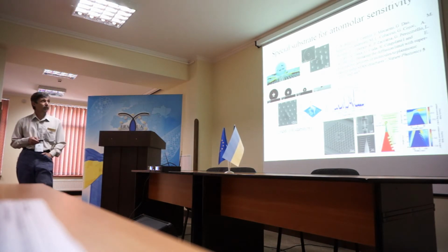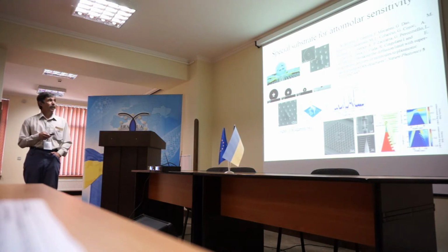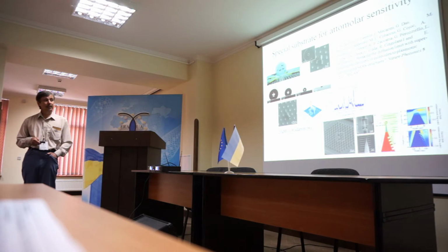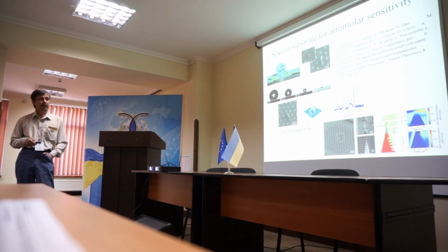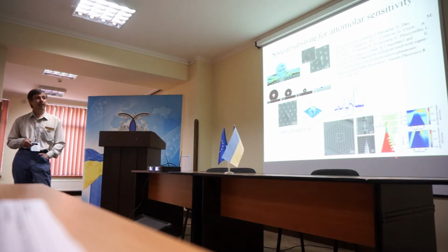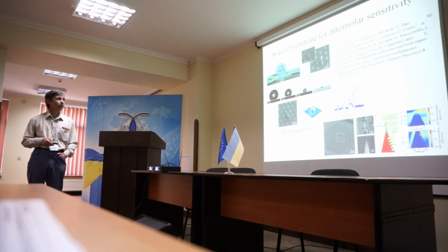So what he proposed is to make an absolutely hydrophobic surface, which is constructed from a number of pillars, and each pillar has a very sharp tip on the top. This pillar is excited by external light, and through this grating, which is made on this tip, the surface plasmon is enhanced. It is enough to register the SERS signal just from the apex of this tip.